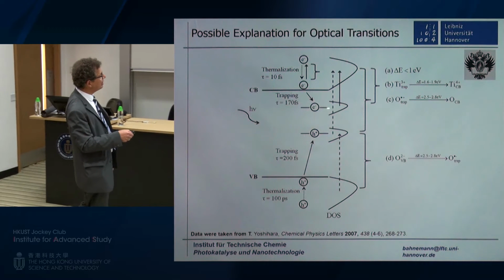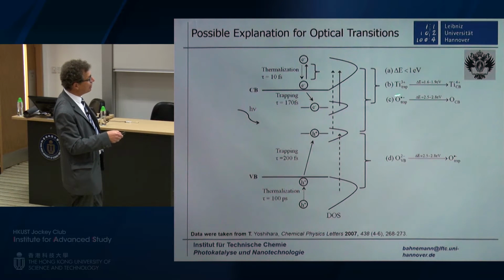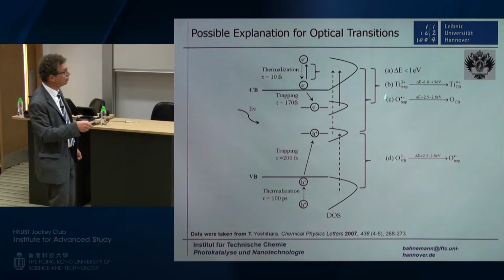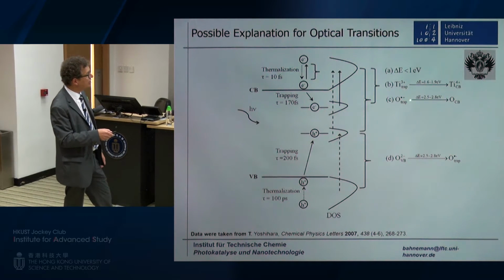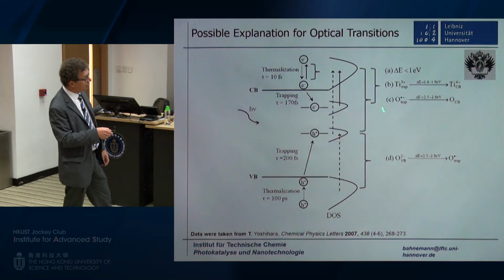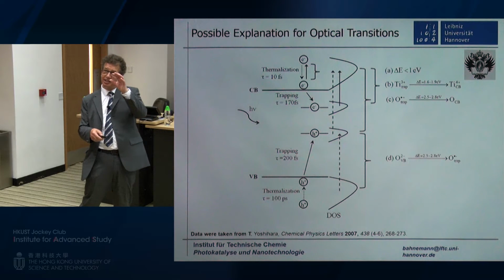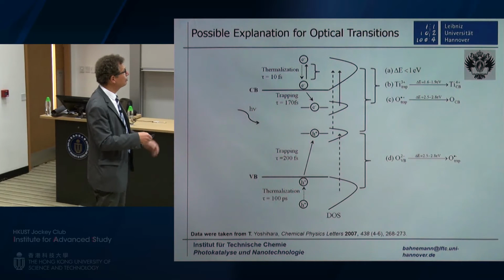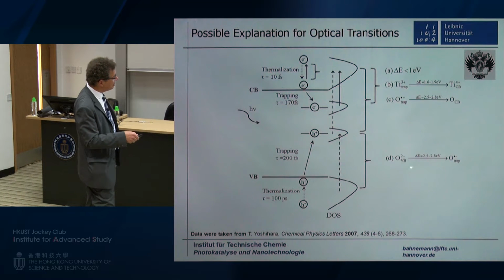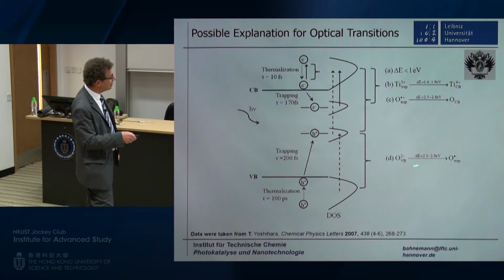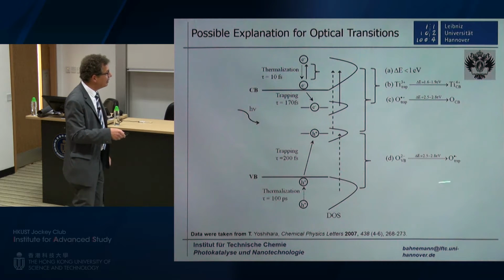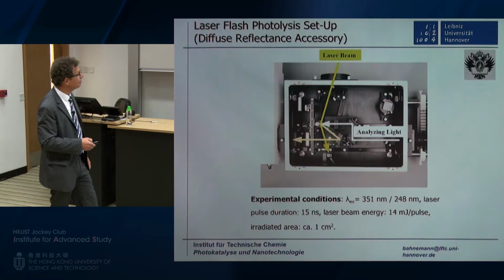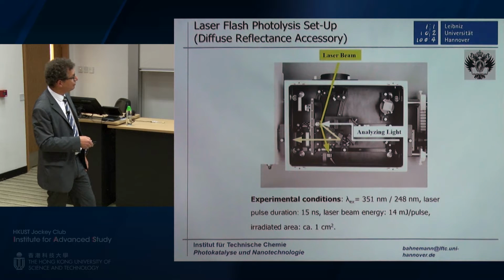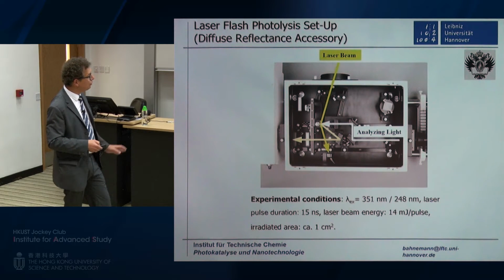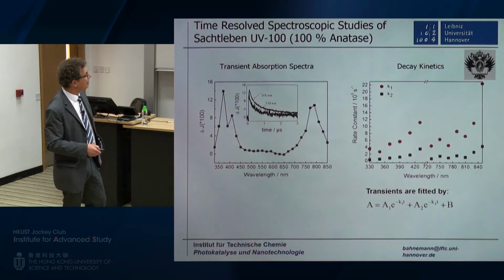And what are these transients? Well, the trapped electron is, as I showed you before, trapped on a titanium 4 site. The trapped hole is most likely trapped as a bridging oxygen, and another trapped hole might be a terminal oxygen here in the system. So we looked at powder samples in reflection mode. That's the first time that real commercial powders have been investigated.